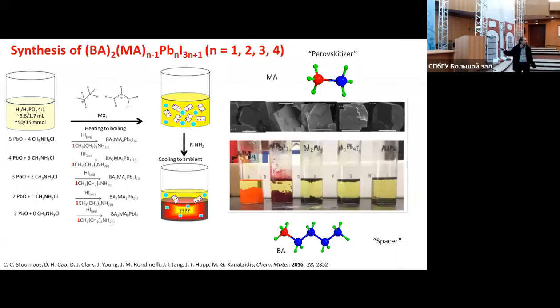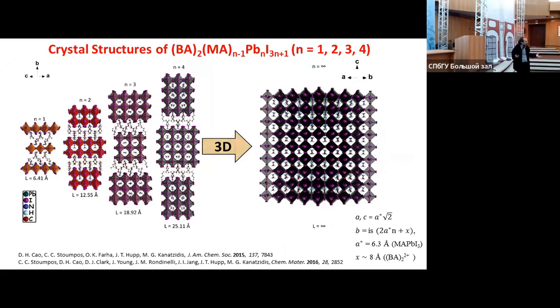We went into the lab and we synthesized materials, not these exact materials, but similar ones. Basically, these materials belong to the homologous series, where you have the butyl ammonium, these longer molecules. Obviously, this cannot fit in the cavity, and it separates the layers one by one. But if you choose the stoichiometry of the chemical reaction carefully, you are able to isolate the materials in pure form, and you can essentially control the optical properties. And once you have this done, we have been able to solve the crystal structure. Look how these materials actually look. And you can go from the monolayer to the bilayer to the trilayer to the tetralayer, and so on.